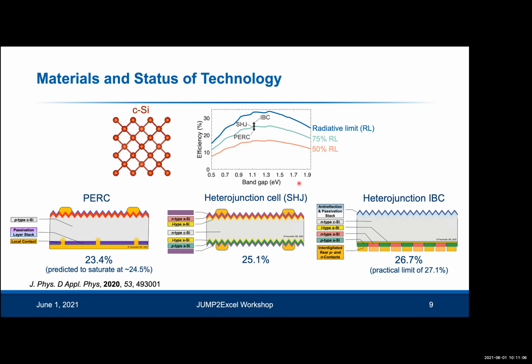There are other device structures which aren't as common in industry right now, but which can give us higher efficiencies. So there's the silicon heterojunction cell. In this device, both the front and back surfaces are passivated by amorphous silicon. You can see there's intrinsic amorphous silicon as well as N- and P-type doped amorphous silicon for charge extraction. This passivation method is very successful. It's led to the highest open circuit voltages among silicon devices. But the disadvantage of this device structure is that the amorphous silicon absorbs light, so it gives rise to parasitic optical losses, which limits the short circuit current densities.